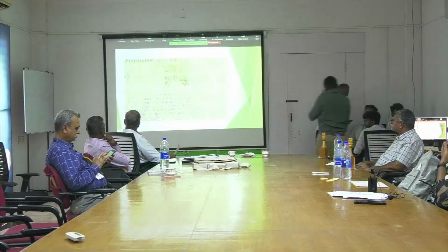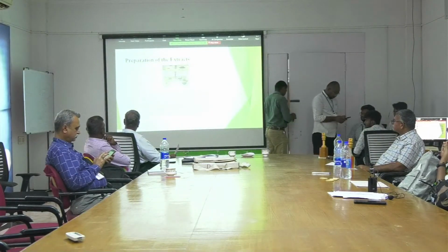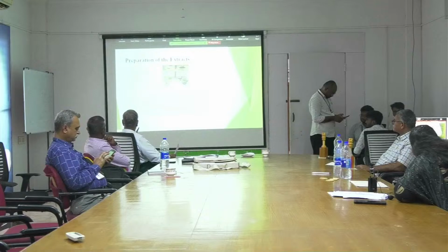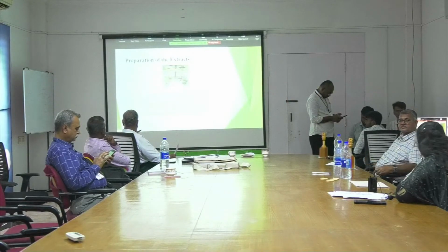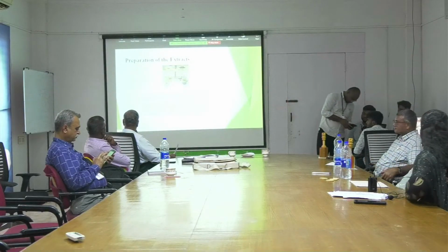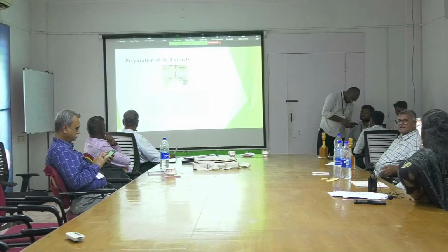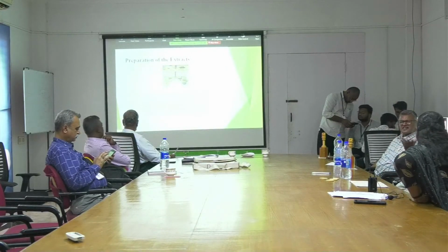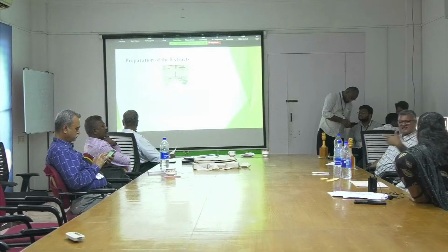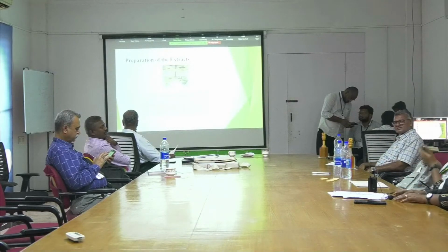Preparation of extraction. Collected Tridax procumbens roots and leaves. Shade-dried plant material, 25 grams powdered, was extracted with 75 ml of 100% ethanol and allowed digestion for 72 hours. The resultant extract was concentrated and transferred into a 250 ml iodine flask. Similarly, root extracts were prepared and the experimental schema is shown in the figure.